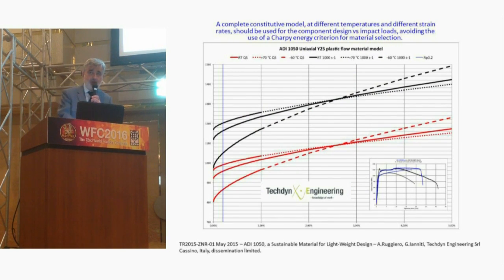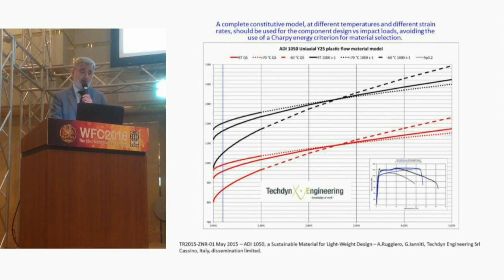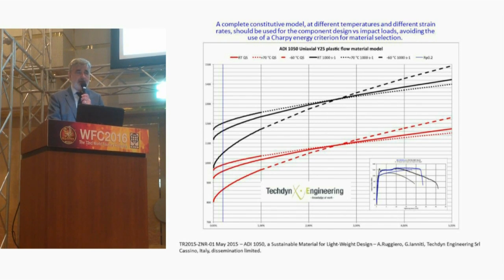And this is a representation of the complete constitutive curve that we did with the Cassino University in Italy, Professor Bonora, with the ADI 1050, where we have tested at quasi-static and at the Hopkinson bar, 1000 seconds^-1 strain rate, at different temperatures, -60, 70, and room temperature. This enabled us to design our castings for shock at high impact loads.